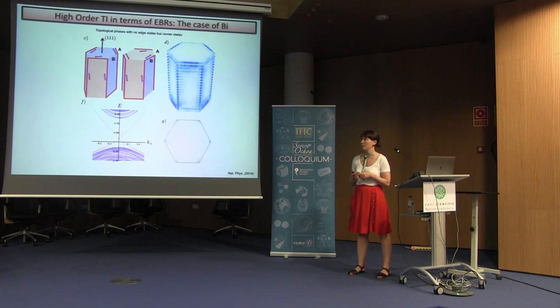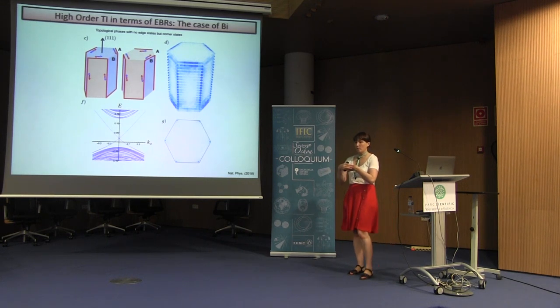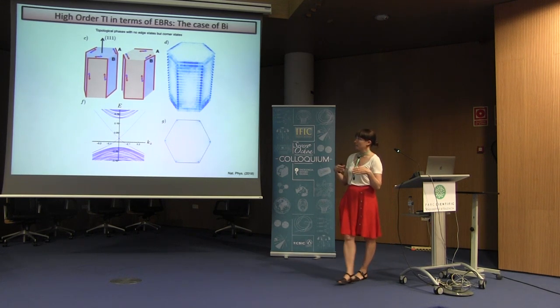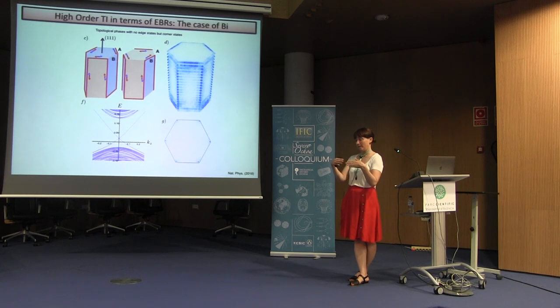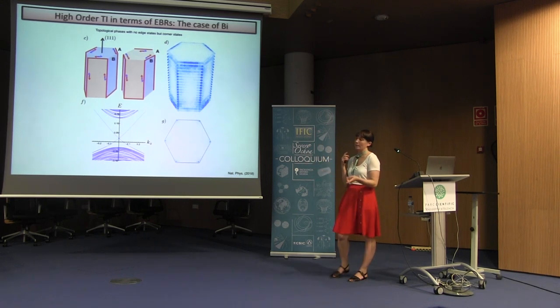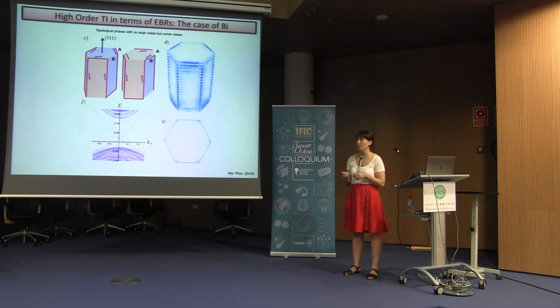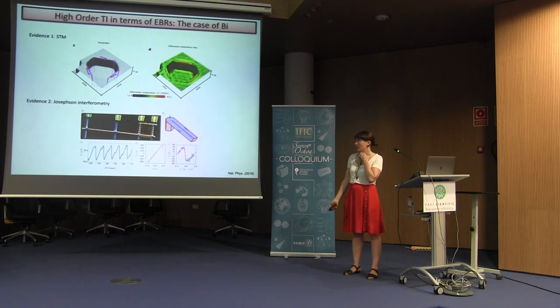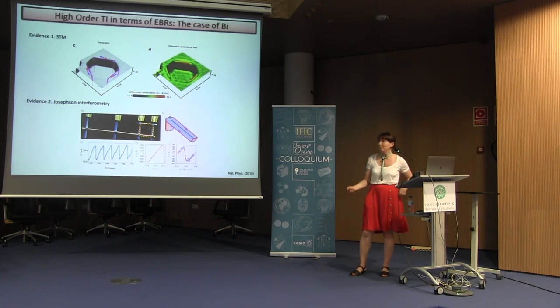So in the case of bismuth, where this charge goes is to the corners of a nanowire. So we need to decouple these two subspaces where the two topological phases are happening, and when they decouple, we see that the two spin channels that I introduced before are happening at the corners of the surface. And somehow, there is some experimental evidence that this was the case.